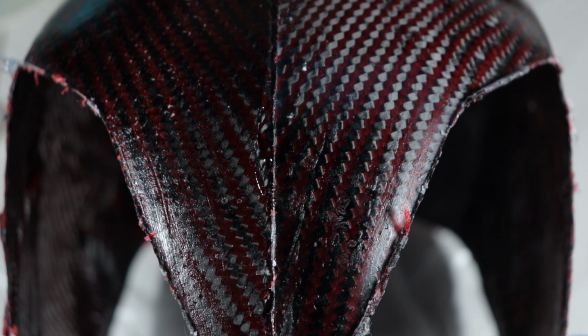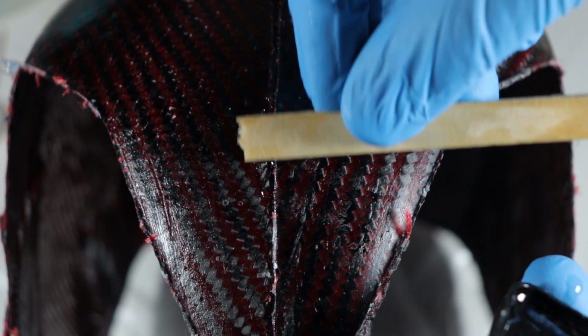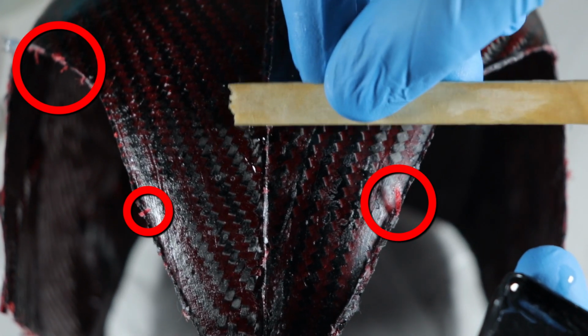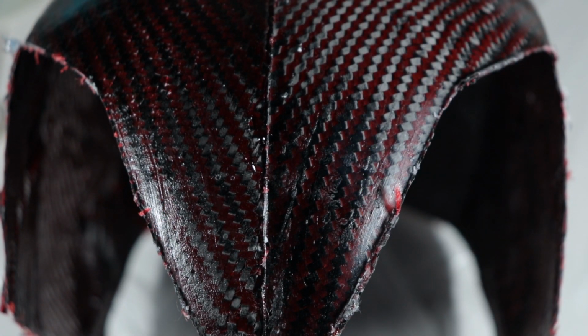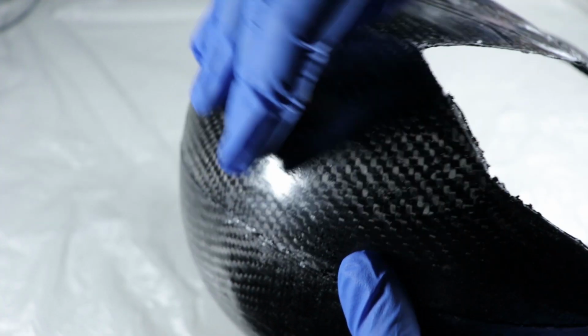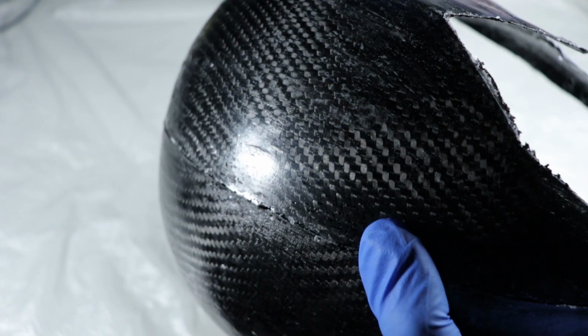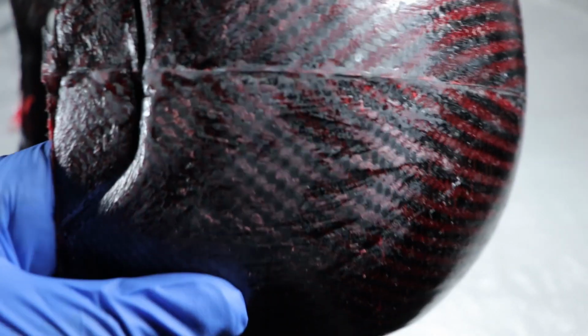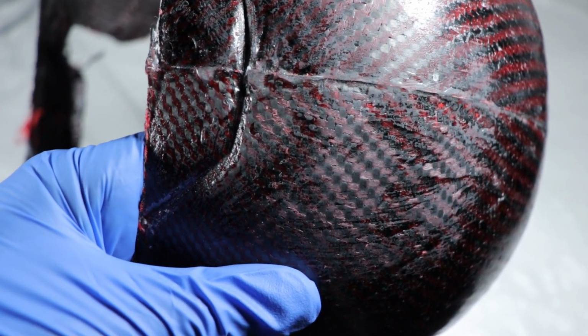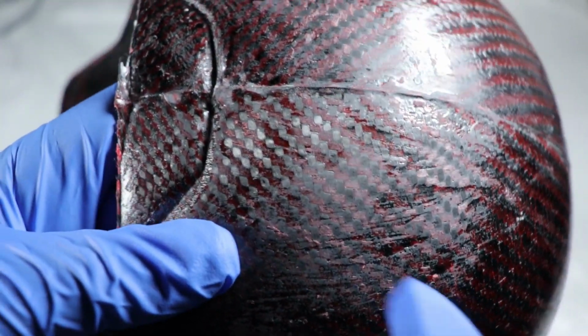As I said before, this hybrid carbon is not easy to use. You can see on the edges that despite using a super sharp knife, the cut is not clean at all. And sanding the surface is even worse. If you sand too far, usually with a carbon fiber fabric, you still have room for mistakes and it doesn't show up that much at the end. It's even hard to see. This fabric gives you very little room for mistakes. And if you sand too much, you will end up with a very bad surface finish.